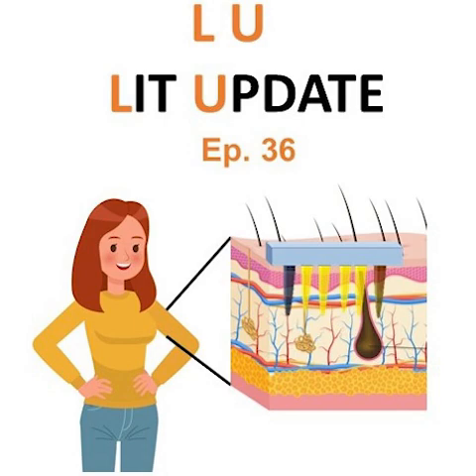And the research was conducted by scientists from Israel and China, and it was published at the beginning of 2022 in the Journal of Advanced Materials. Now, these scientists developed a microneedle sensor platform that can monitor sodium levels in real time. So the solid microneedle was made of polystyrene that was then coated with titanium and gold to make the working electrode. And then another set was coated with silver for the reference electrode. The sensor operates through the extended gate field effect transistor mechanism. In field effect transistor-based sensors, the current that is flowing through the semiconducting material changes as the biomarker concentration changes. And in this case, a sodium selective membrane composed of sodium ionophore X, some sodium surfactants, and also some polymers was placed over the sensor.